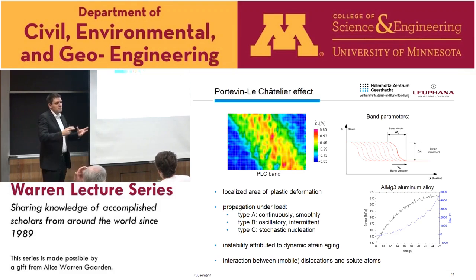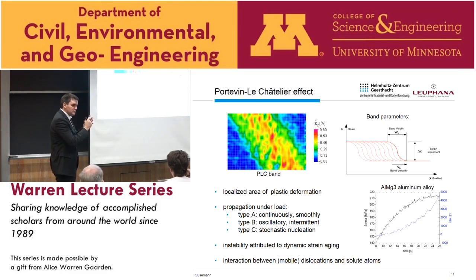This instability is usually attributed to dynamic strain aging. Imagine it this way. You have these solute atoms inside of your material. Then you have a number of dislocations. They are attracted by these solute atoms, and then they are stuck there for a certain time. So there's somehow a kind of cloud, I would say. You need to overcome a certain stress level, and then this cloud is released, and you have these bands inside of your structure. This is of course the interaction between the mobile dislocations and solute atoms. It's always the mobile dislocations.